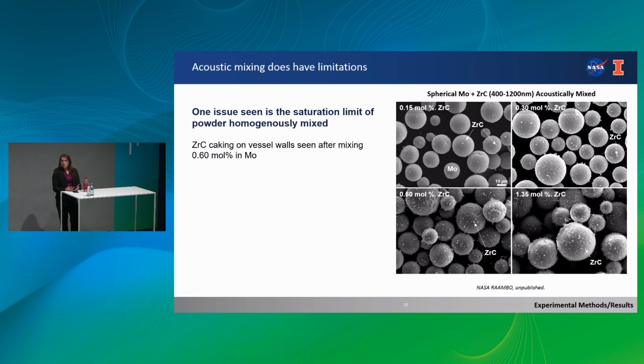One issue with this approach, though, is that you get a saturation limit of how much of your material you can add. We added 0.6 mol% and 1.35 mol% of zirconium carbide, and as you can see, the difference between these two is very similar. We actually started to see a buildup of the zirconium carbide on the mixing vessel walls after adding 0.6 mol% zirconium carbide. So you have to be careful how much material you're actually adding and find that saturation limit.